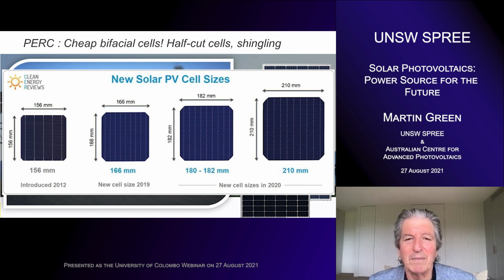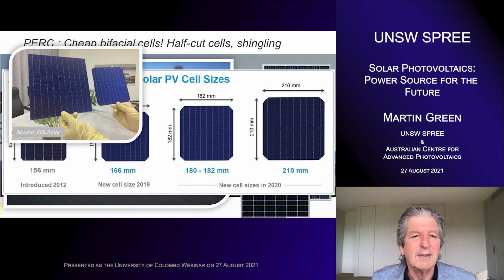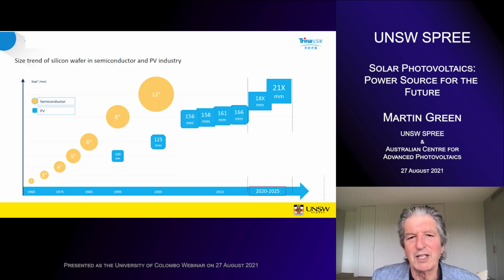So they're now 8-inch, or even bigger, 210 millimeter square wafers, which are now the largest used by the industry. Most manufacturers are now using either 182 or 210 rather than the 156 size. So you process the wafer as a whole, and then at the end of the processing, you just cut it up into the individual cells. So you save on the processing costs by doing that. That just gives you an idea of the relative sizes of the cells.